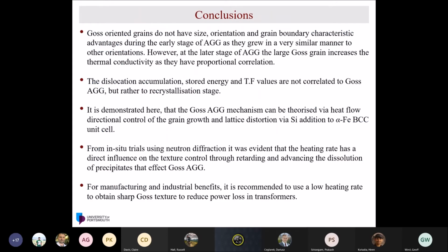Next slide. I think this is my conclusion. So in my conclusion, I can say from our experiments of more than 5 years, and except my previous years, 15 years ago, we come to the conclusion that Goss-oriented grains do not have size or orientation or grain boundary characteristic advantages during the early stage of abnormal grain growth, but rather all these advantages come to life at the late stage of abnormal grain growth, including the grain size advantages, orientation advantages, and 20 to 45 high mobility grain boundary. And the dislocation accumulation, stored energy, and Taylor factor analysis is actually very relevant to the recrystallization stage, but you shouldn't find any correlation with the abnormal grain growth stage.